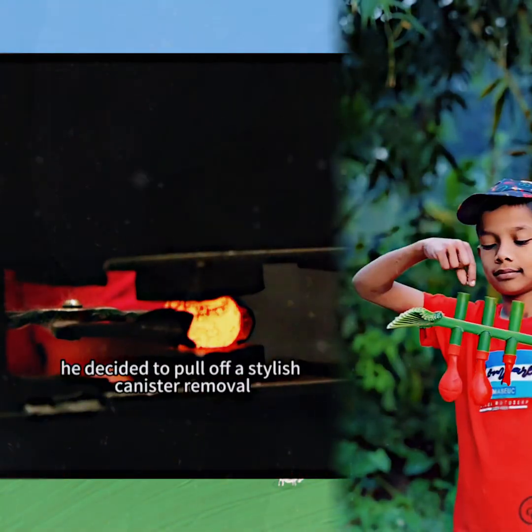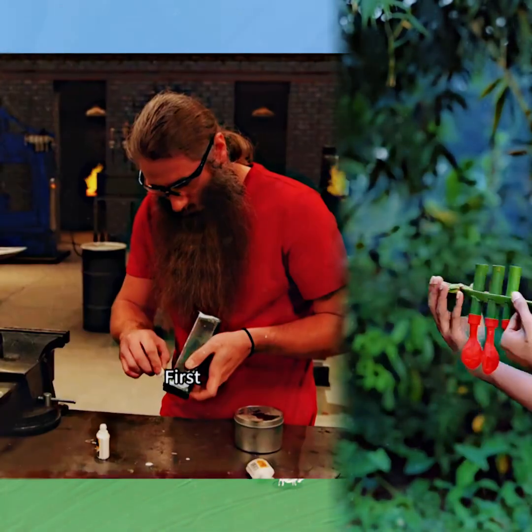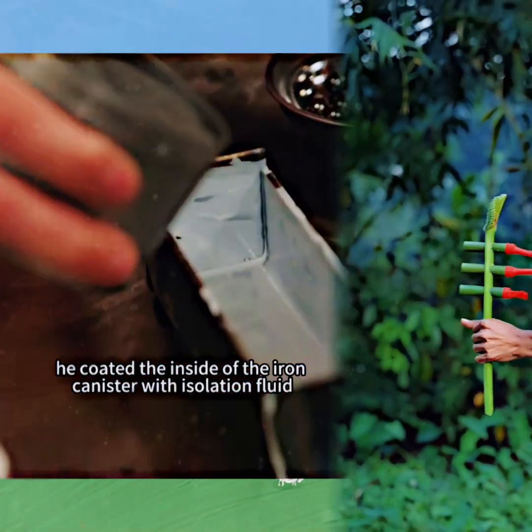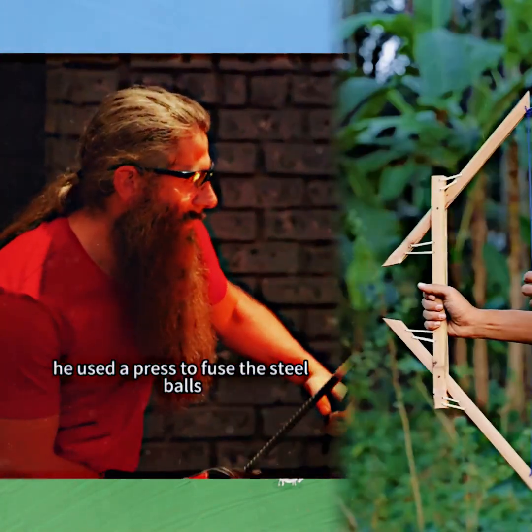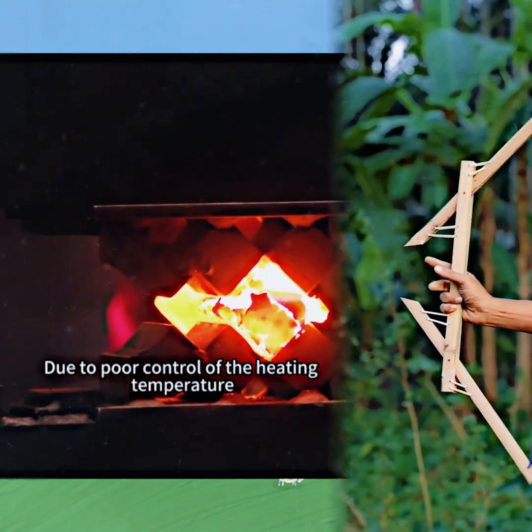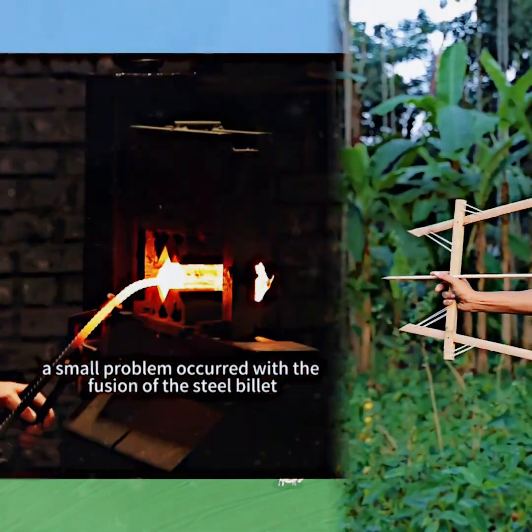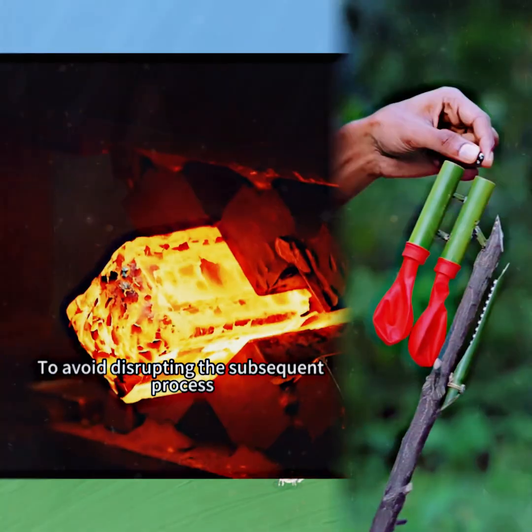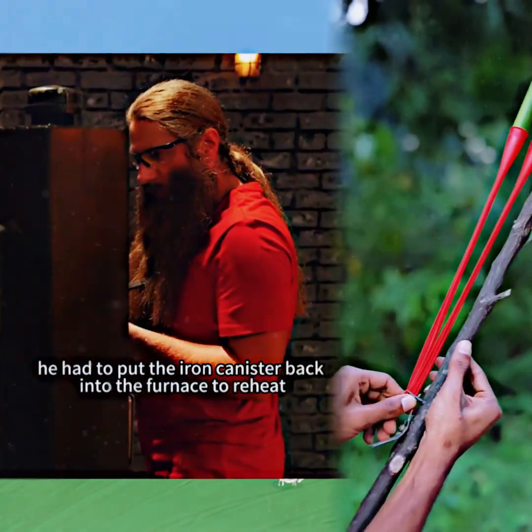This time, he decided to pull off a stylish canister removal. First, he coated the inside of the iron canister with isolation fluid. Then, he used a press to fuse the steel balls. Due to poor control of the heating temperature, a small problem occurred with the fusion of the steel billet. To avoid disrupting the subsequent process, he had to put the iron canister back into the furnace to reheat.